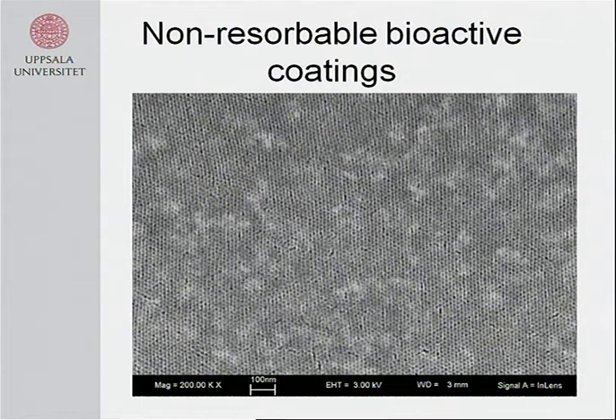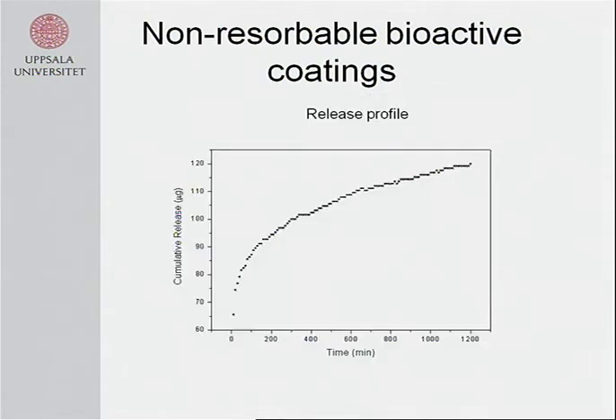This is another route. It's a non-resorbable bioactive coating where we could tailor the pore structure of the non-resorbable coating for loading and slow release of drugs. So the other coatings will resorb and go away, and this one will stay for a very long time, during the implant lifetime. We have done just some initial loading and release. In this case, it's also on antibiotics. After 1 day, we have around 20% of the total loading released. So this is also an ongoing route which we're pursuing.